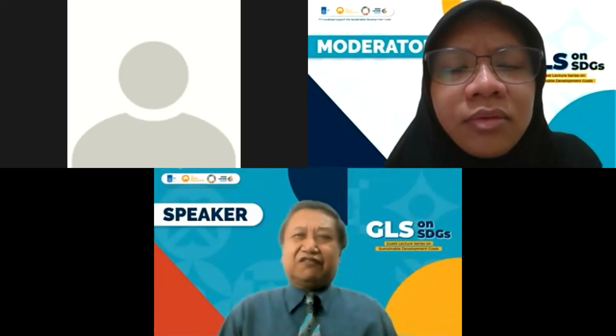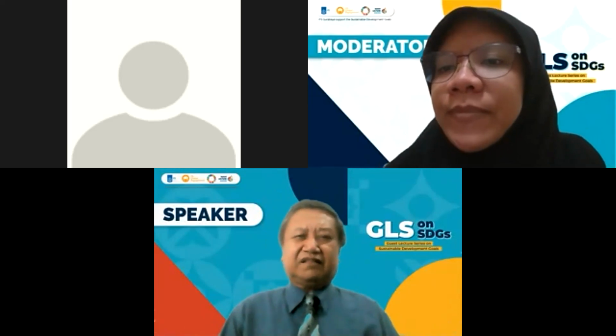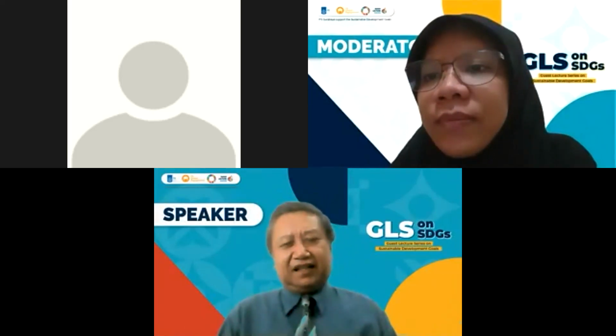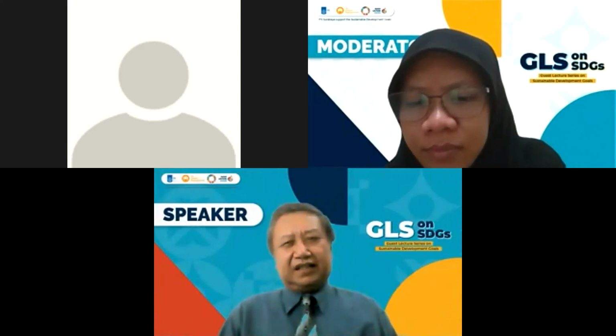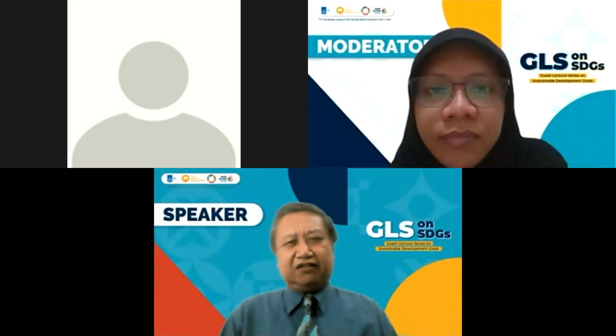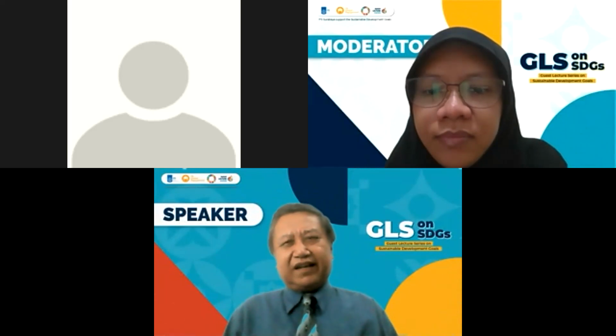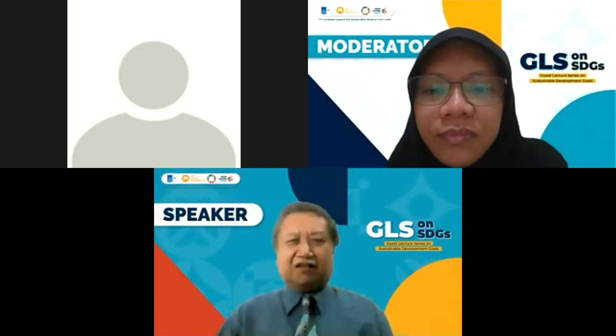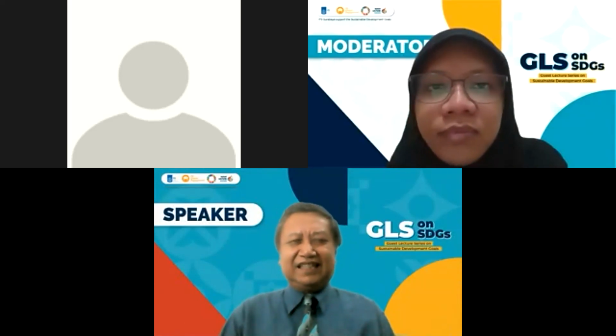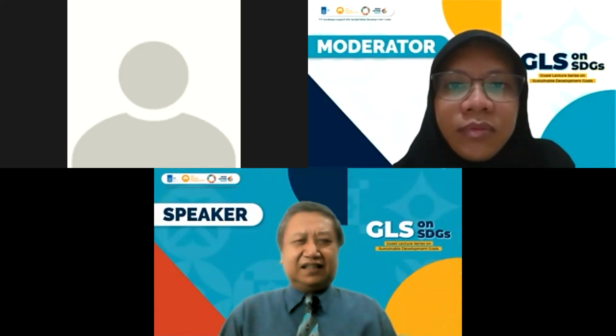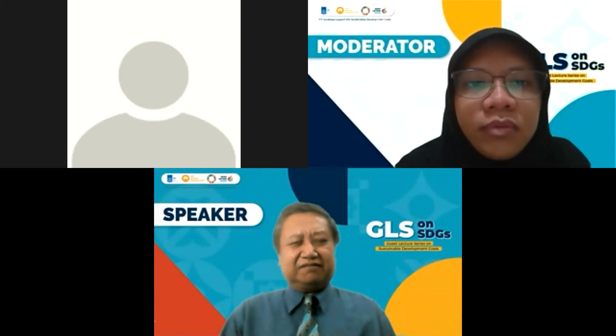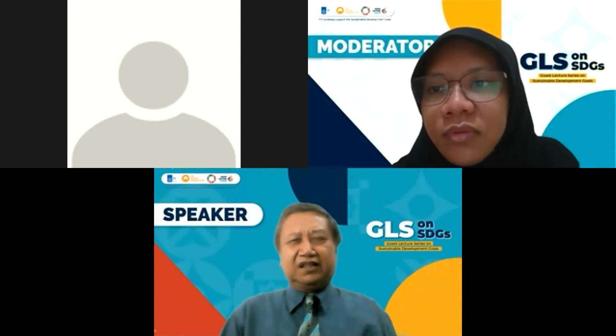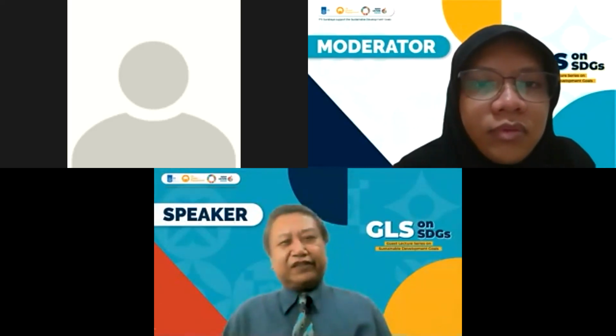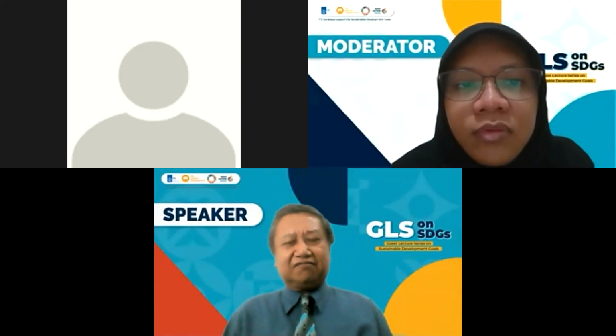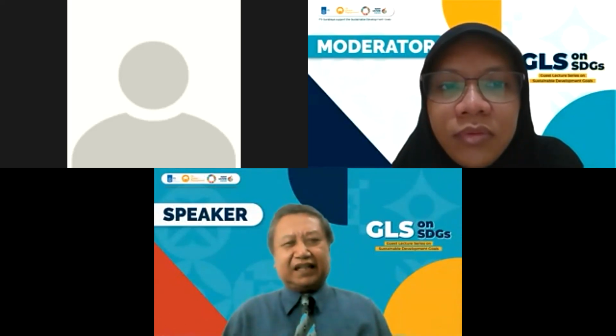Okay, thank you. So for the first attempt to check the RGO and GO, according to the XRD spectra analysis, GO has the longer interlayer distance. The diffraction peak of GO is around 10 degrees, whereas for RGO there are two peaks around 23 to 24 and 42 to 43. And according to the oxygen content, the graphene oxide has much higher oxygen content, around 50 to 60%, whereas in the RGO the oxygen content is only around 9 to 15% and so on.